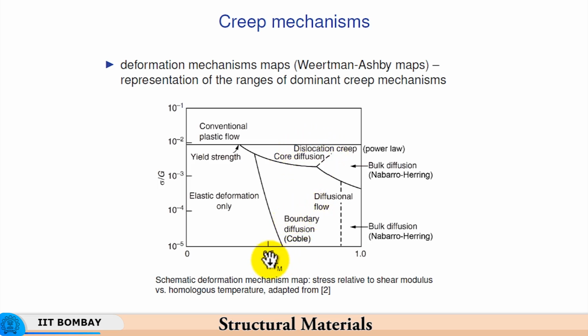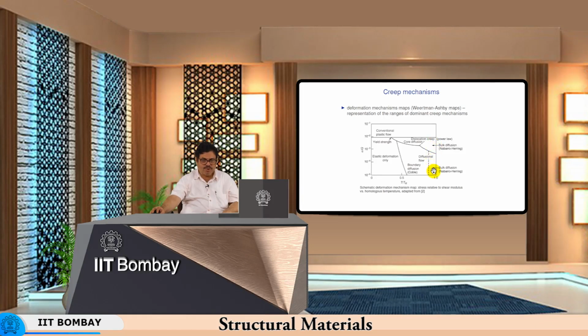On the other hand, with increase in temperature, even at low stresses, there is enough driving force for grain boundary diffusion to take place, as in case of Coble creep. So, Coble creep will occur at relatively low stresses, but temperature being the same and stress being high, you have dislocation creep taking place, aided by the vacancy diffusion. And then here you see that there is bulk diffusion taking place at high temperatures and even low stresses, because the driving force is sufficiently large as to cause vacancy diffusion through the lattice. So, bulk diffusion means diffusion of vacancies through the lattice. So, here you have bulk diffusion even at higher stresses as well as the lower stresses.